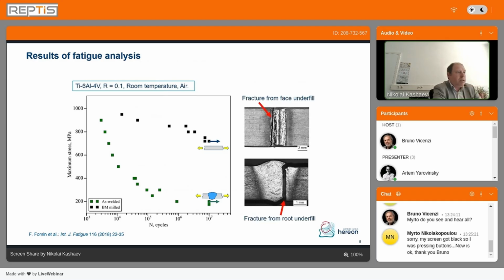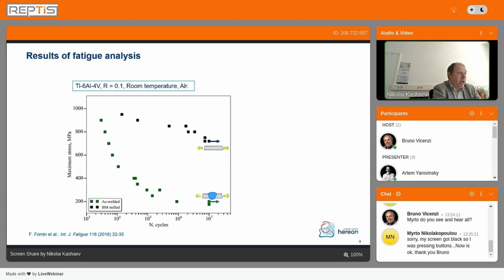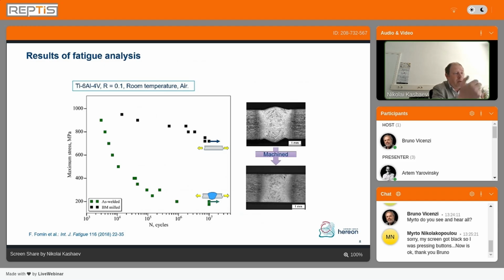The first important reason is the presence of geometrical defects. The crack typically initiates from geometrical imperfection, fracture from the root underfill in this case. One possible way to improve the situation is, for example, to remove the geometrical defects, for example, using a machining process, and then we are already in the improved condition. We are significantly higher with regard to as-welded condition, but we are still below the level of base material.